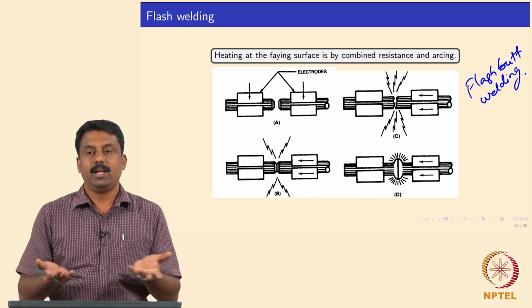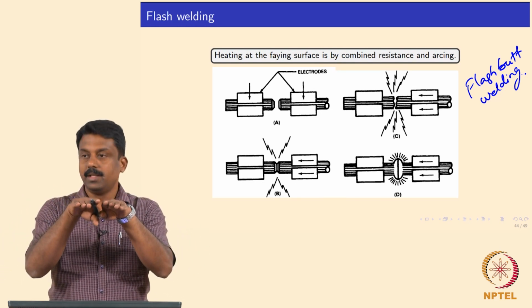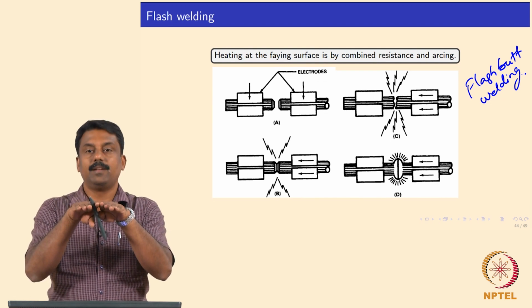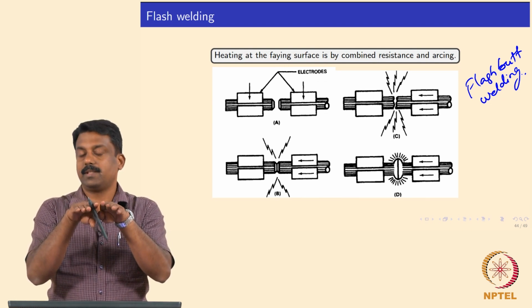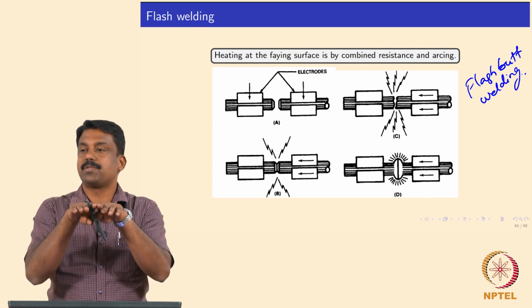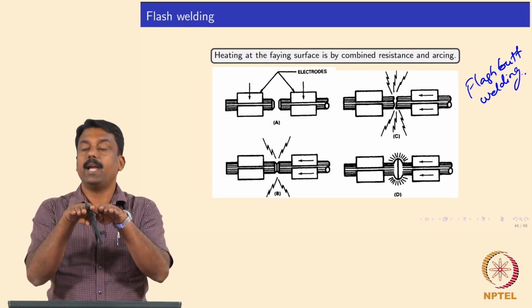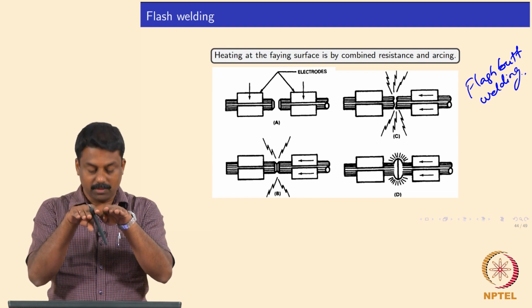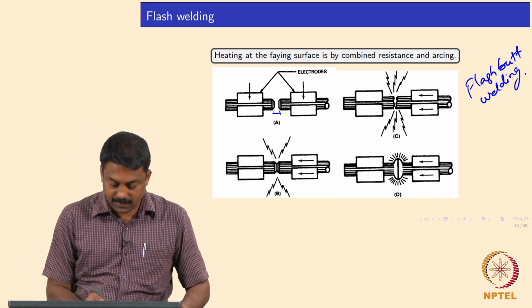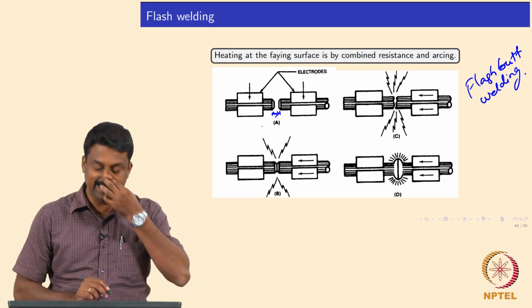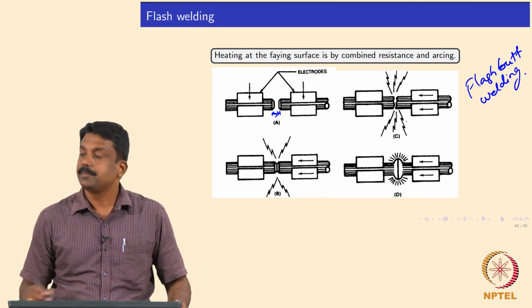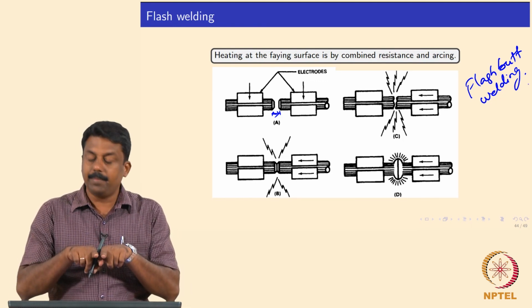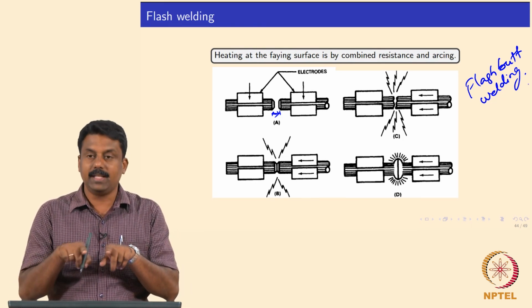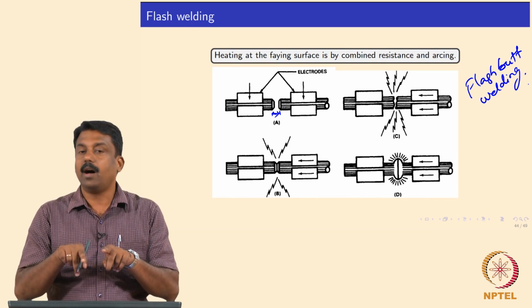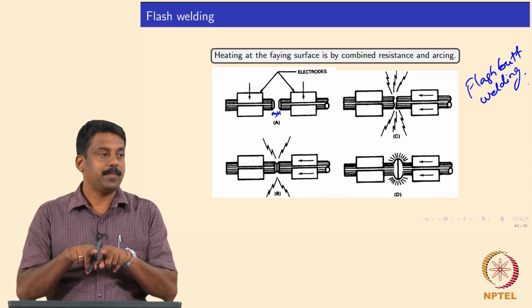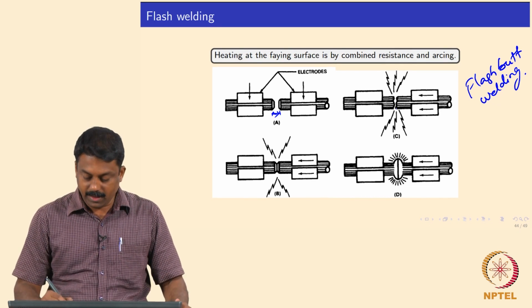You have a flat sheet, it is rolled and brought into contact with each other. In flash butt welding, the mechanism works in such a way that we don't really keep both sheets together in contact. We maintain some gap, as shown over here, between the faying interfaces. Then you pass a current. When you maintain a gap and pass a high frequency current, you will start arcing, isn't it? Arcing would lead to the melting of the interface.